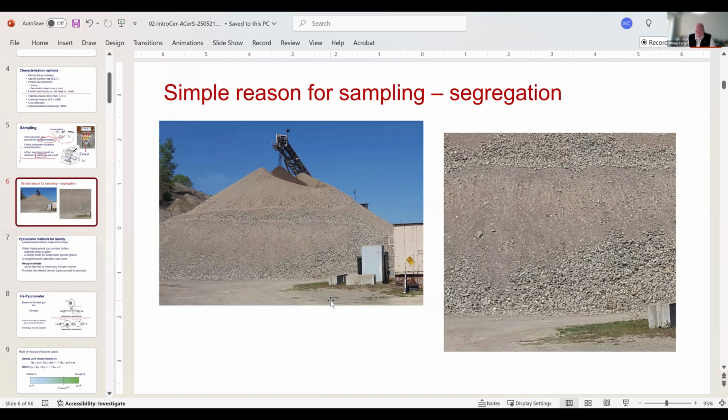and then it gets separated and it gets poured into a large cone, if you will. Okay. And with this cone, there's a number of things here. One is you get a specific angle here, which is called an angle of repose. It's a natural angle for the material. So you can't stack it higher than that level, or else when it gets to that point, friction takes over or whatever, and the material will move.